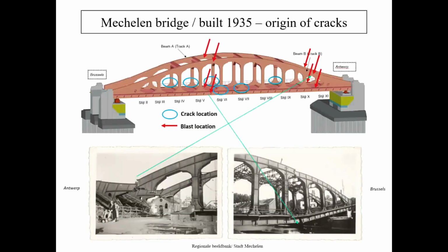To make it short, the committee found that the bridge had some heritage value, meaning deemed to be listed. The committee also agreed that the most probable cause of cracking was the blast loading of May 1940, and that the cracks had remained unnoticed since then, because there is a good agreement between the location of the explosives, and therefore the fractured zone, and the positions where the fine cracks were observed. Relatively good correlation.